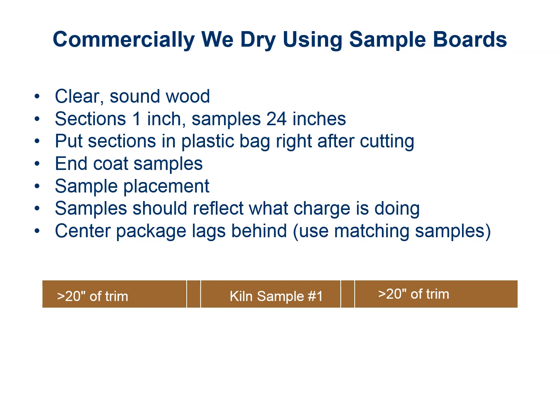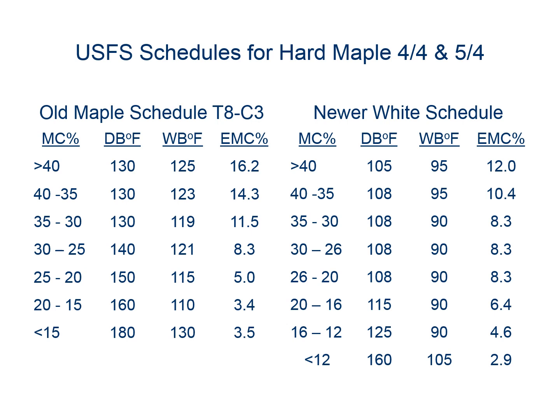As the lumber is drying, we let the air get drier and drier as we go, and what that allows us to do is to monitor how fast we want to dry, and all the wood species have different rates that we want them to dry. This is the hard maple schedule, both the old traditional one on the left and a newer, milder schedule. And if you notice, the big difference is how hot the kiln gets. The dry bulb degree Fahrenheit column on the left goes to 180 degrees. The one on the right stops at 160.